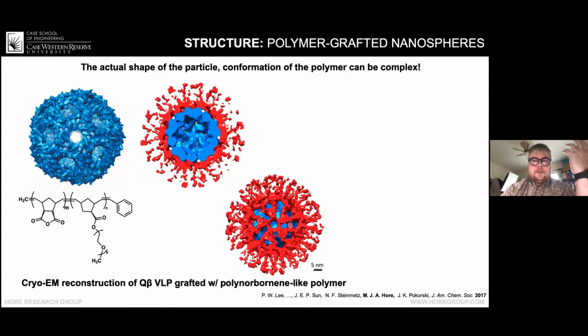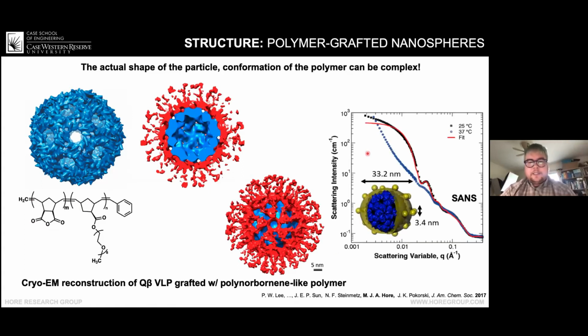What happened in terms of the actual experiment is we did the neutron scattering first, and we saw this very odd-shaped curve, which says to a scatterer, oh, you must have this raspberry-like structure. Then we went back and looked at the structure of these particles. But you can't always do that. You don't always have the contrast in the electron microscope to see this. So if you think about the earlier image I showed you where researchers are using TEM to look at the brush thickness, the point I'm trying to make here is that you're missing a lot of potential detail in what the particles have.